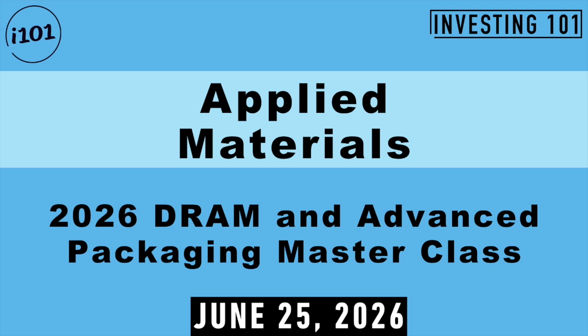3D DRAM requires building an ultra-tall stack of more than 100 alternating layers of silicon and silicon germanium. The superlattice is formed using advanced epitaxy. Maintaining tier-to-tier uniformity across hundreds of horizontal layers is essential, since variations impact electrical performance. A major materials engineering challenge is managing interfacial stress within the silicon germanium lattice, which has a higher lattice constant than silicon. Without control, lattice mismatches can generate defects that increase DRAM cell transistor leakage and variability. Applied is using its epitaxy leadership to tune surface chemistries and process conditions that help customers achieve high film quality